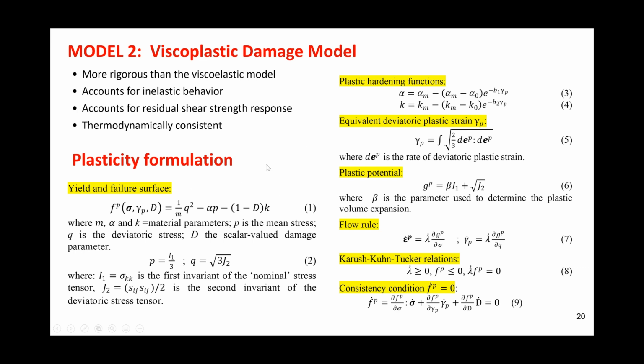Here's the plasticity part of the model. We have a yield and failure surface, a function of Q and P, and the damage parameter D. Okay, so we have 3 parameters, M, alpha, and K. Okay, they are obtained as curve fitting parameters. So the failure surface is nonlinear. Okay, it's hyperbolic actually. Where P is the mean stress and Q is the shear stress.